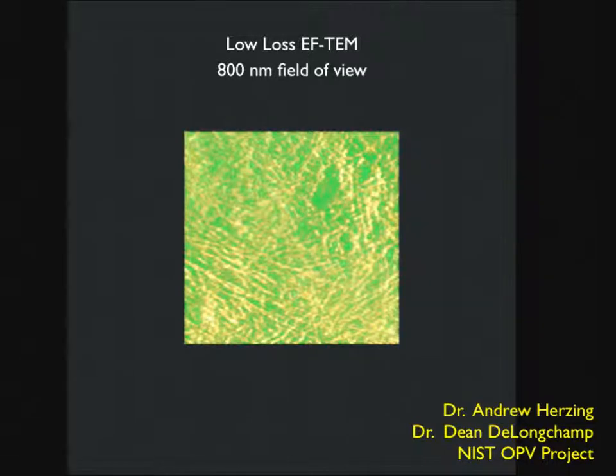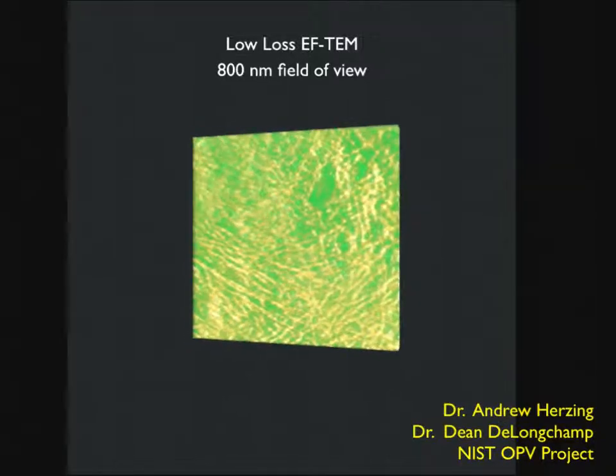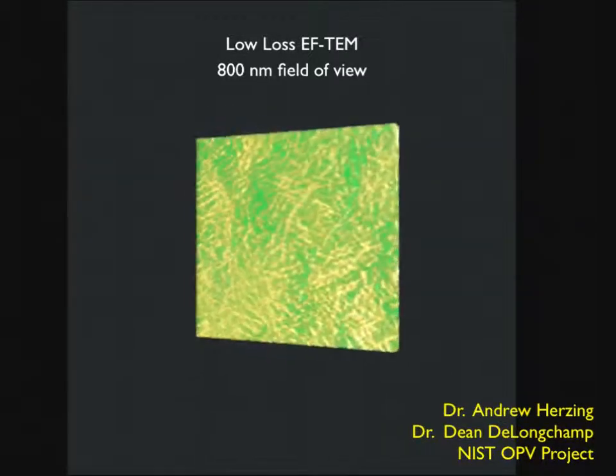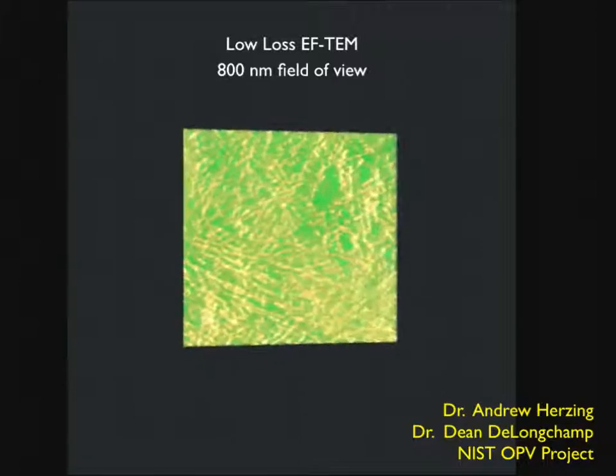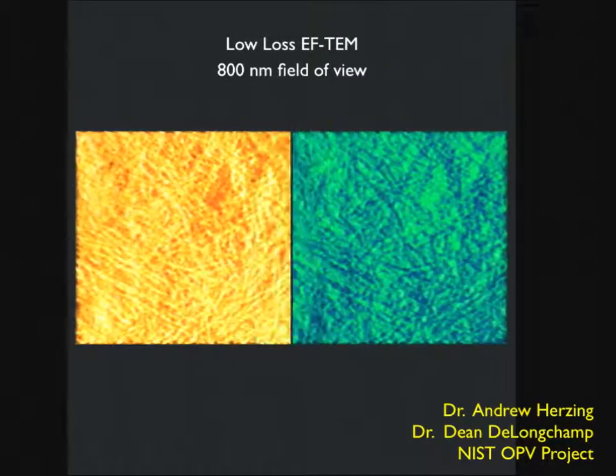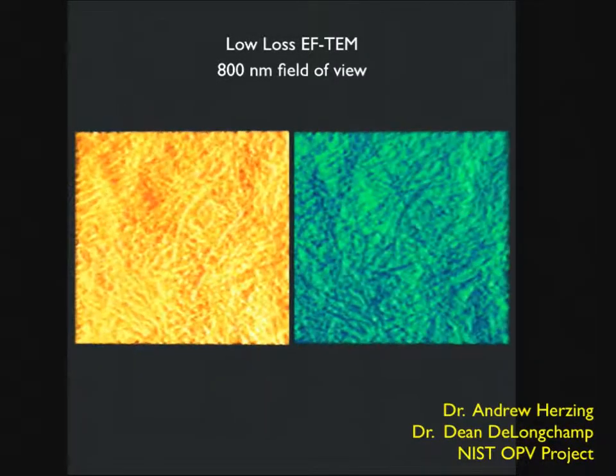And this is an example that was provided by Dean DeLongchamp's group at NIST, and they have some of the best instruments in the world for this. So this would be an 800 nanometer field of view. And in this case, the red component, which we'll separate out pretty soon, is the polymer component, and the green component is the fullerene. So what you see is some linear structures, some nanofibrils. That's a result of self-organized growth of the polymer. And then the remaining structure is the void space that's filled with fullerene.